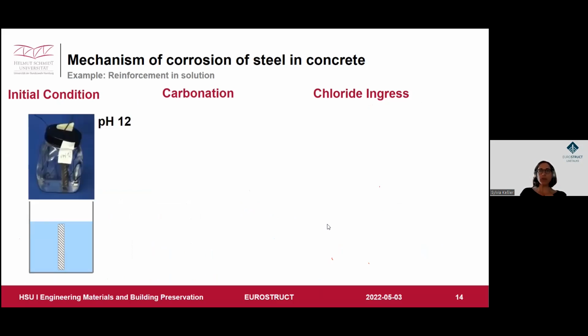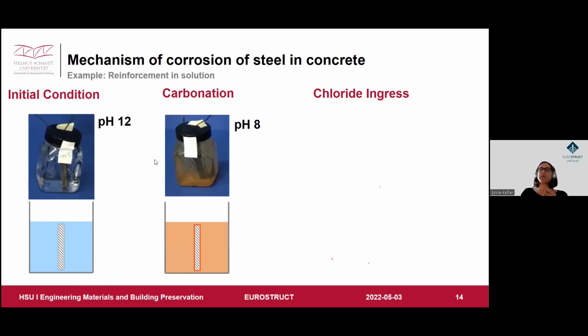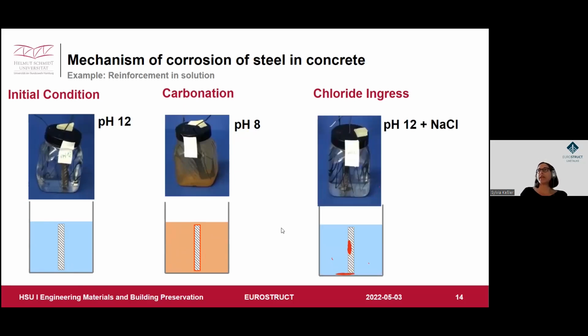So what I normally do for my lecture, we place a normal reinforcement in a solution with a pH of 12, comparable to the concrete. Here you see the sketch, the water stays colorless, so there was no corrosion product at all. For the carbonation, we place a reinforcement in a solution with a pH of 8, which is comparable to carbonated concrete. And here we see the brownish color, so a lot of iron oxide has been produced, the typical rust. And for chloride ingress, we normally prepare a solution with a pH of 12, and we add sodium chloride to it. And here we can see some iron oxide products at the bottom of the container.